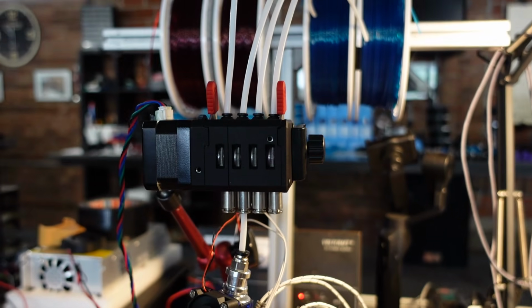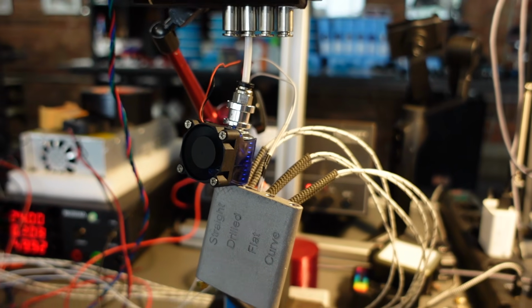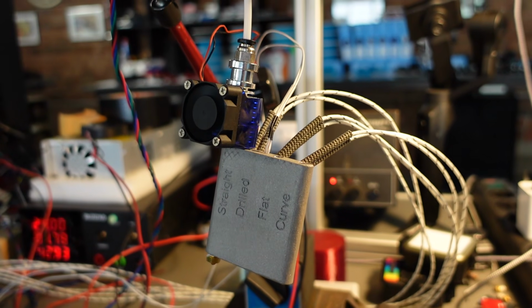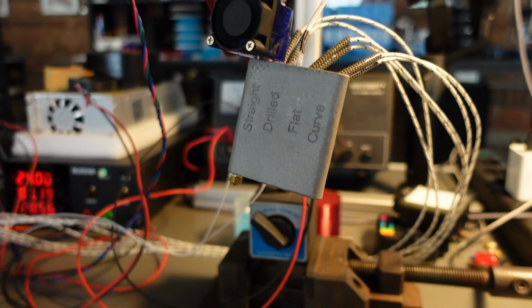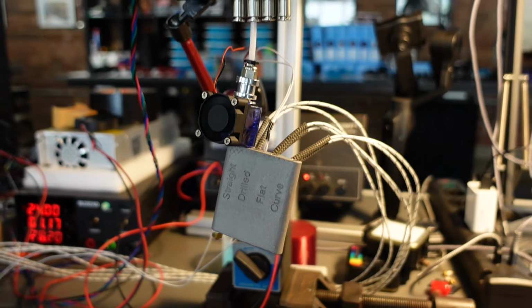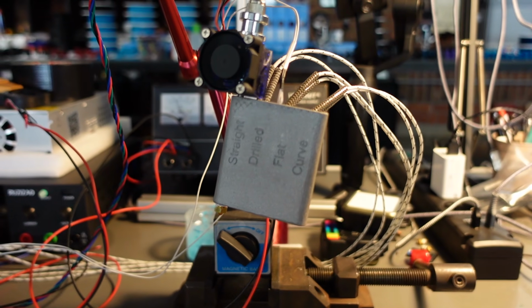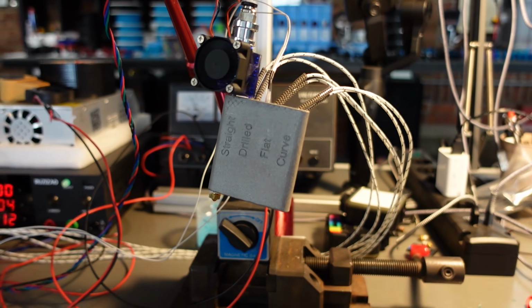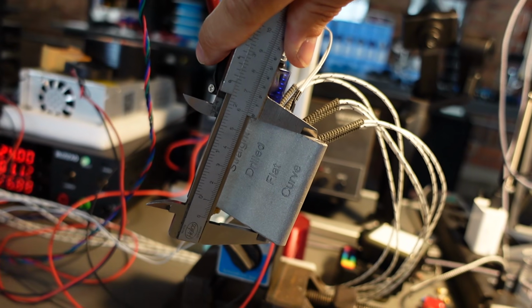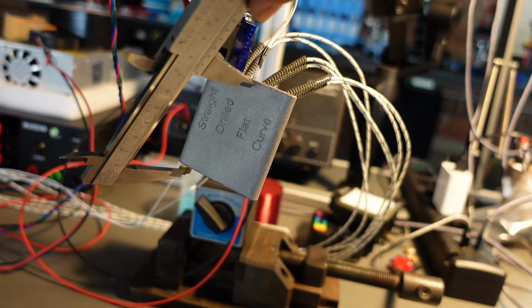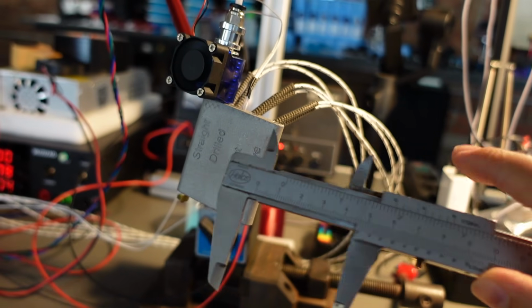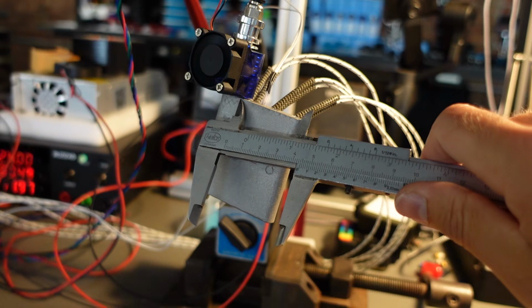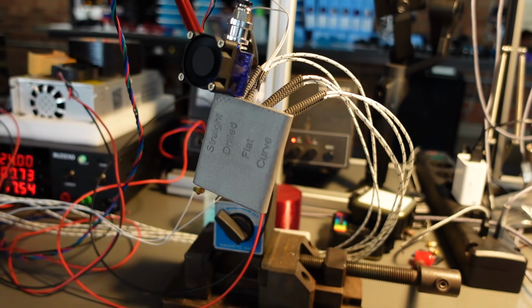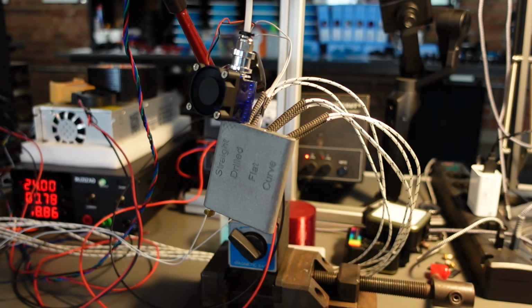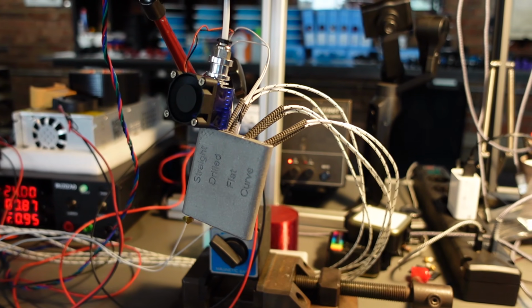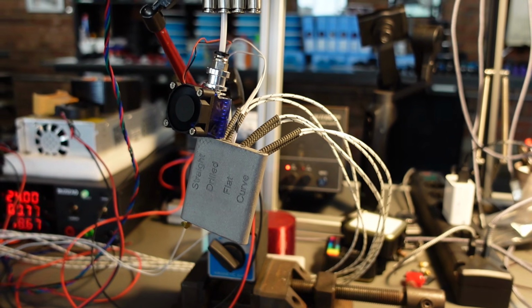And we're set up here. So I just plugged in one of the tubes here, and this is an E3D V6 clone, just adapted with the standard stainless steel heat break, and again the same 0.8 mm nozzle. And this is the straight section, basically straight how it came from the SLM machine. So we're just gonna see what our baseline is. This is 60 mm in length, plus 6 mm of nozzle stick out or something, and then let's say minus 6 mm from the heat break that it's been threaded in. So 60 mm in aluminum. My prediction is that we can run somewhere in the neighborhood of 45 to 50 cubic millimeters a second. That would make sense. Let's see where we're at.